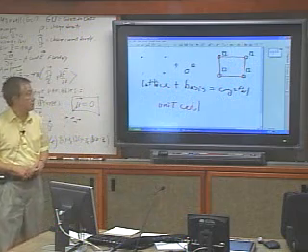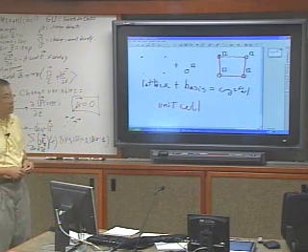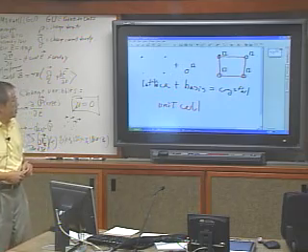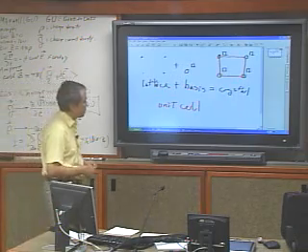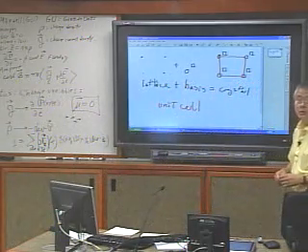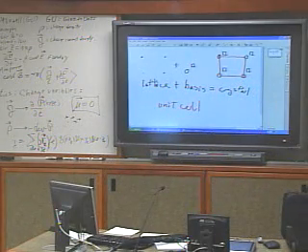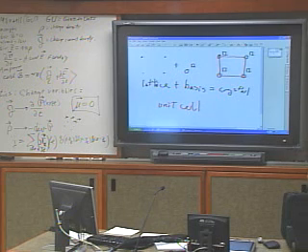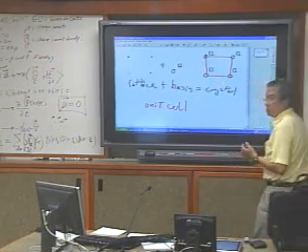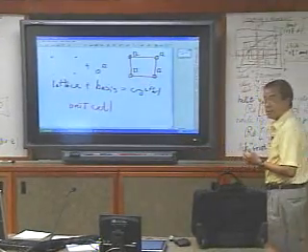And yes, in some sense, the unit cell is a simpler representation, a simple way of describing a crystal, and that's why they do it at the undergraduate level. But it turns out the problem with the unit cell is that it doesn't tell you what the symmetry is, and we need to know what the symmetry is for the reasons I mentioned in the last lecture. You need to really know symmetry, because that will tell you where the atoms are, which is what you want to do if you're doing diffraction.